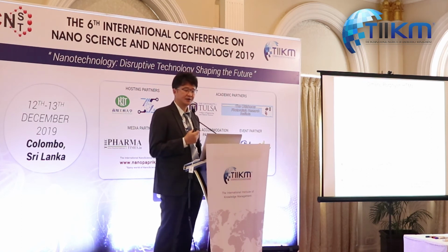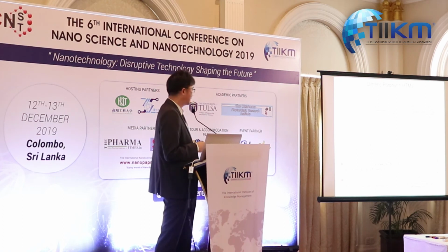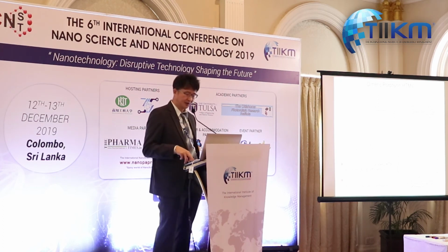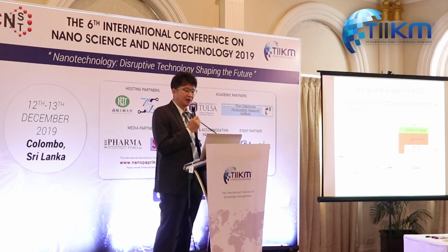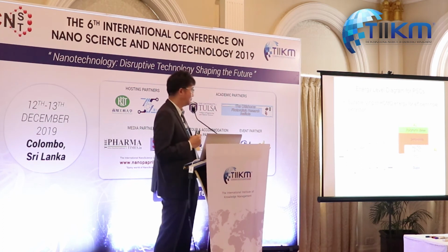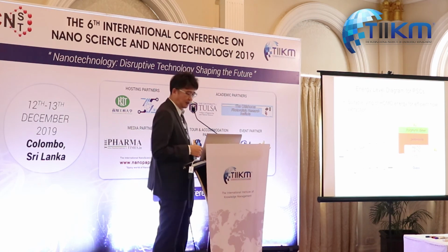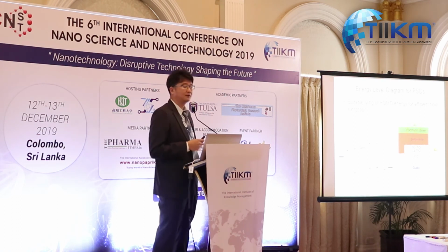So we designed and synthesized these highly conjugated porphyrin dimers as hole transporting materials. These dimers show slightly upshifted HOMO energy level, and the device is composed of FTO and compact titanium dioxide, mesoporous titanium dioxide, perovskite, porphyrin dimer, and gold.